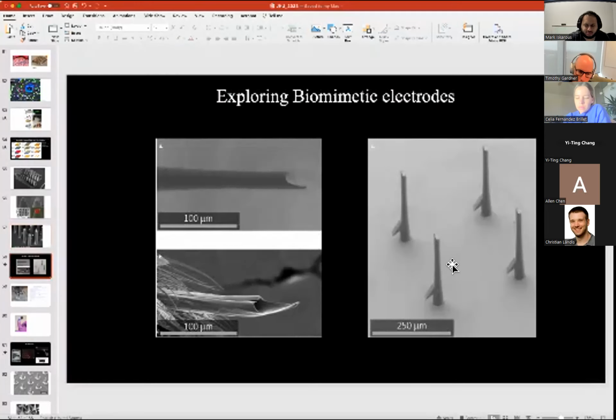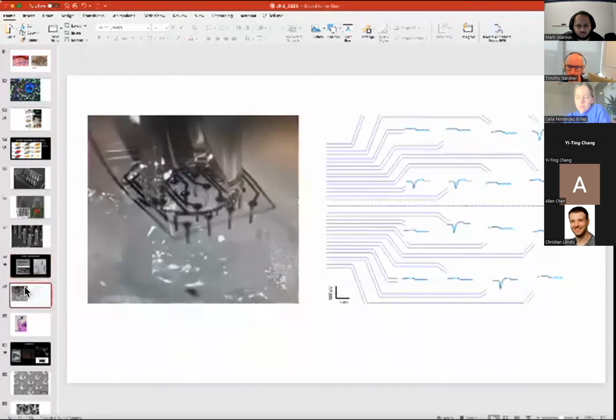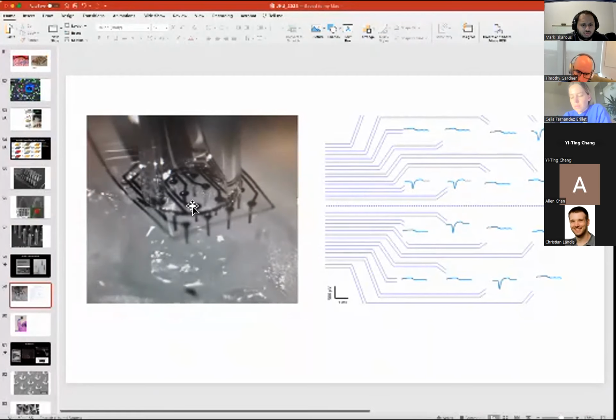And so the student in the lab that's working with that has gotten down to about 5-micron needle sizes that are freestanding, up to 350 microns tall. And I think that'll allow us to increase the density of the needles before we hit that bed of nails effect where the brain just kind of dimples when you try to insert it. So we're pretty generally excited about this form factor.